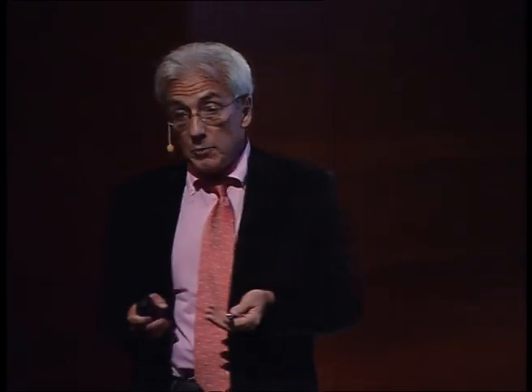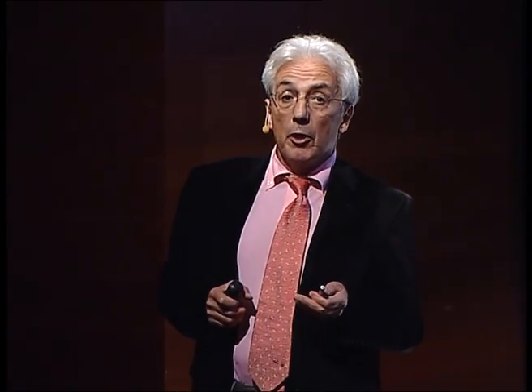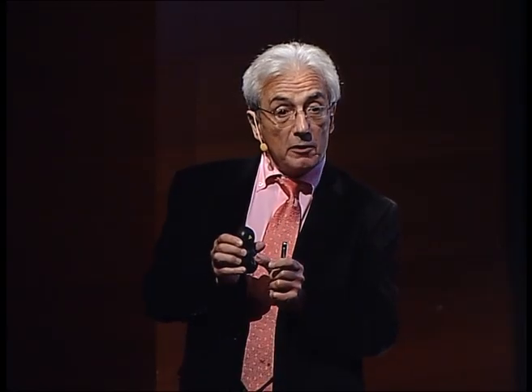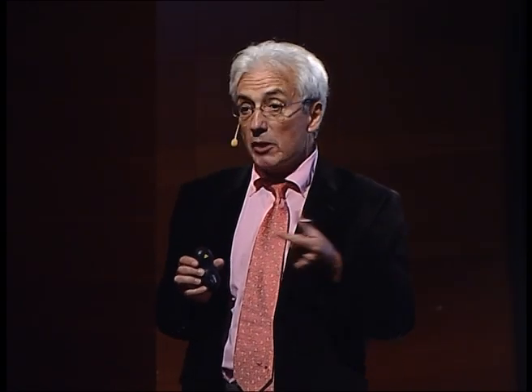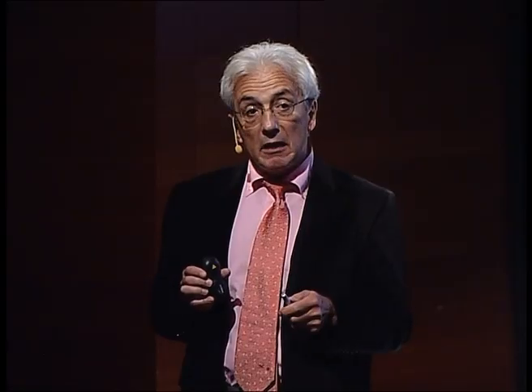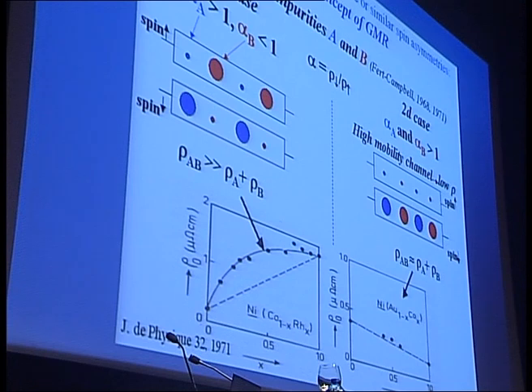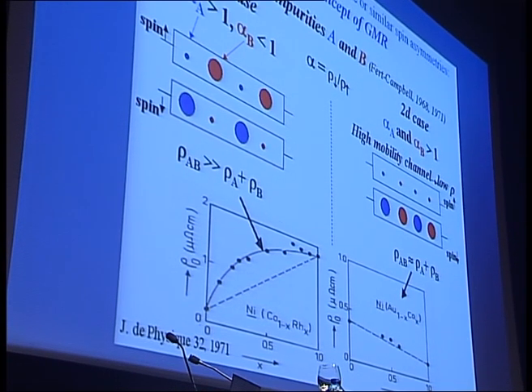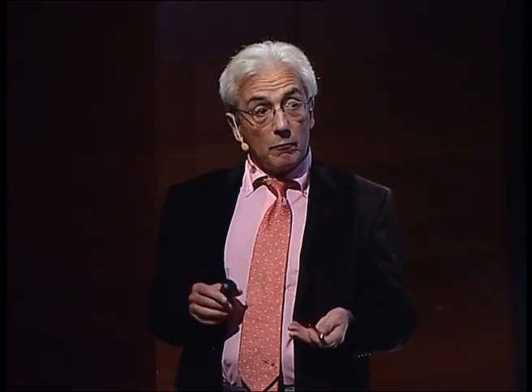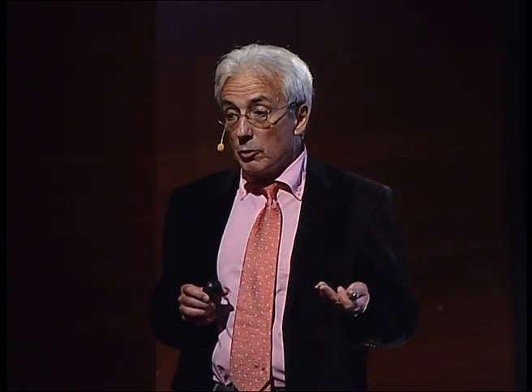But if we know the transport equation, you know that the electron will be able to feel the relative orientation of the two layers only if the distance between the two layers is smaller than the mean free path of the electron, which in this metallic layer is of the order of a few nanometers. So at this time, it was not possible to prepare multilayers with a thickness of only a few nanometers. The nanotechnologies were not accessible. And so this sort of concept was requiring an advance, the onset of nanotechnology.